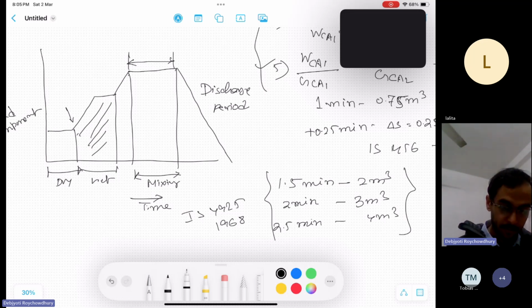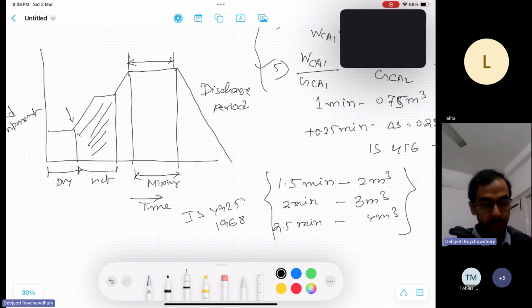Excessive mixing also leads to segregation for lean concrete, meaning concrete that is not designed in a specialized or desired way. So for lean concrete, it will segregate. For the purpose of this mixing, the tilting type mixer is not desired, and the bottom discharge mixer is desired. Whenever there is a tilting type, the aggregate has a tendency to come out fast, then later the paste will come. However, in the bottom discharge mixer, this problem doesn't exist.